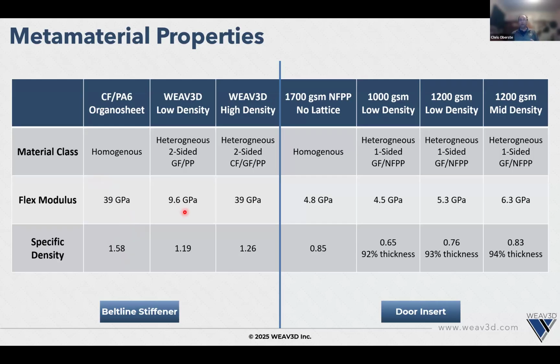When we go to the low density lattice, where we had the wide spacing between the tapes, we're only getting a modulus of about 9.6, and we're only using glass and polypropylene to do that.